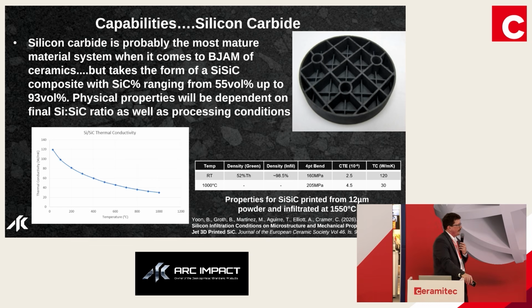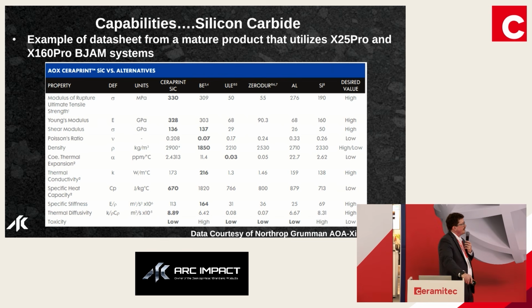At the bottom here, I have a couple properties from one version of siliconized silicon carbide. This is off a paper out of Oak Ridge National Lab in the States, where they were looking at a very specific powder cut and very specific infiltration parameters and varying those parameters to see how it affects the properties, but also the infiltratability of the part. On a more mature side, and this is a user of both the X25 and the X160 Pro systems, they've been doing this for quite some time. They've got a very solid set of properties that they've developed. These are all at room temperature.